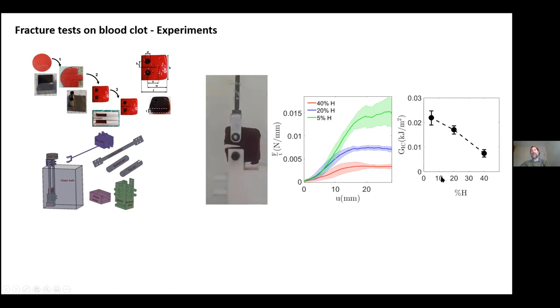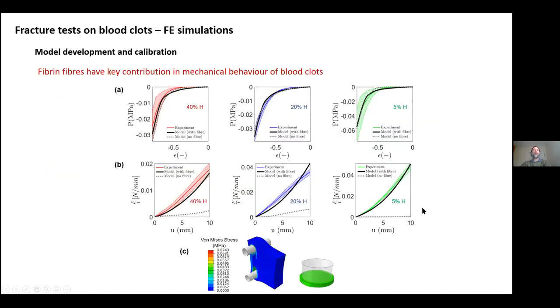So if the hematocrit of the blood solution that we use to make the clot is low, then we have a high fibrin content and we have a high fracture toughness. Whereas if we have a high hematocrit, that means we have a low fibrin content and it's much easier to cause the clot to fracture. So we perform very detailed analysis of the material behavior of the clot, because in order to do a good fracture analysis, you must know how much energy is being stored in the material.